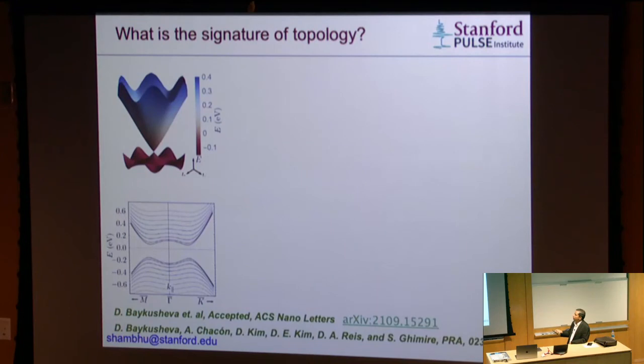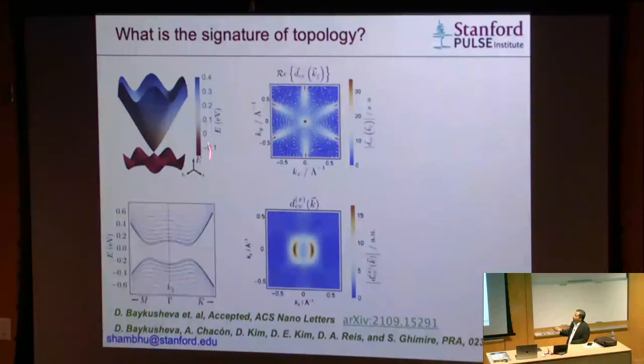So this is again the calculated band structure. We start from the tight binding model. This is the bulk band. This is the surface band. So we have this nice single Dirac cone here. These are the transition dipole moments between these two bands, and the same thing here between those bands. And you notice something here, especially here. There is a vortex feature at the center, and that is a reminiscence of spin momentum locking. I'll tell you what it is.